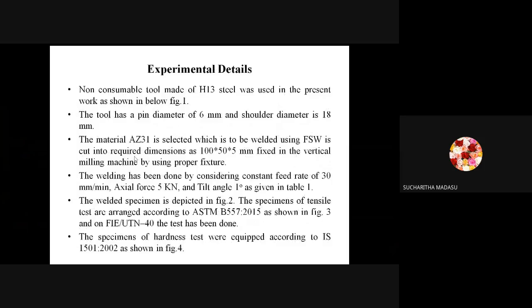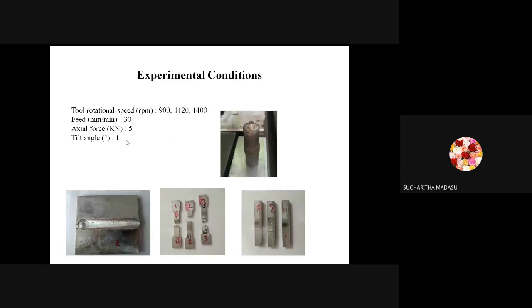So here, when I am coming to my experimental details, I have taken the tool as H13 and the tool dimensions, actually I will show you. The pin diameter is 6 mm, the shoulder diameter is 18 mm, and the material I have selected is AZ31. For this, the welding parameters I have taken: tool rotational speed is the only variable here. Three different tool rotational speeds I have taken: 900, 1120, 1400. The feed is 30, axial force is 5, and the tilt angle is 1.